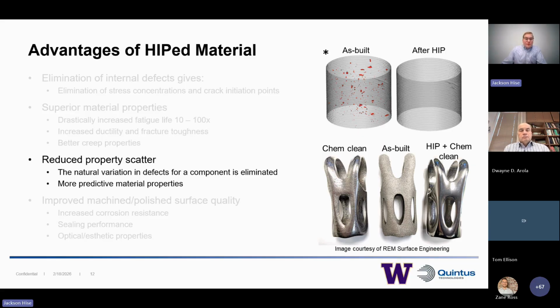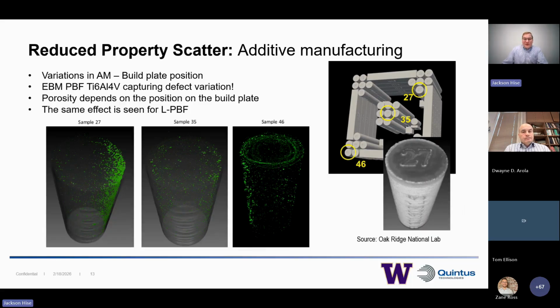We also can think of reduced property scatter. Here we know that there's natural variation of defects between components being built. One example in the additive world is even among the single build plate, variations across the build plate produce different defect locations. So here we can see sample 27, sample 35, and 46, and where these defects are scattered throughout the part. By HIPping this, we can resolve these internal defects, providing not only a fully dense sample, but also predictable variation between each and every component.